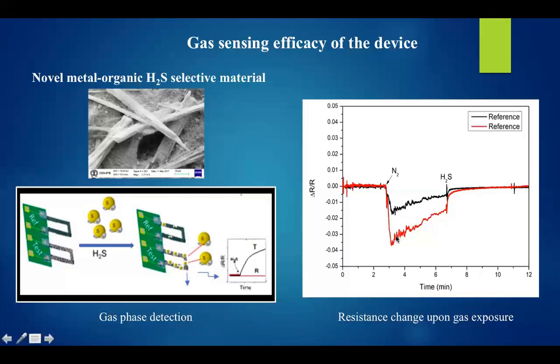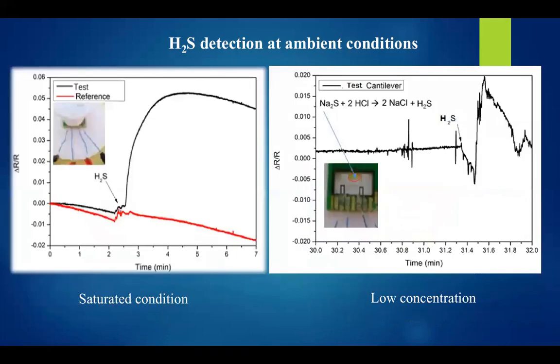The first experiment we did was just to see how the sensor behaves in presence of nitrogen. Both the cantilevers were reference cantilevers without any selective coating on them. But in case of nitrogen, we saw that there is a change in resistance of the cantilever. So we did not use nitrogen, the usual carrier gas, for these gas sensing experiments.